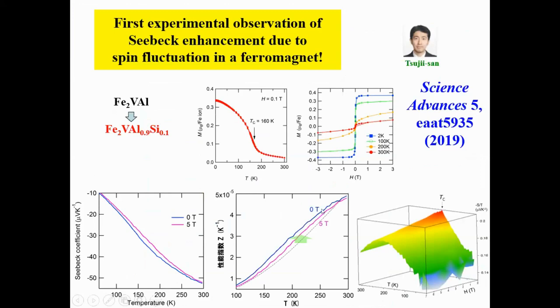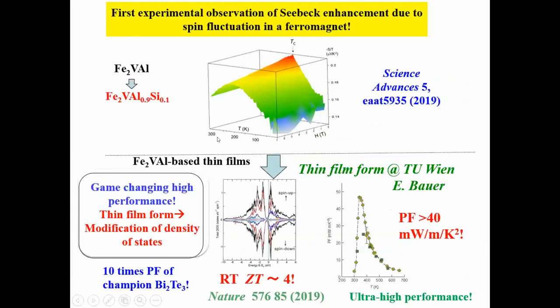And basically, this was proved by applying a magnetic field and suppressing the spin fluctuation, which shrinks the Seebeck, as shown here. And actually, this effect looks to be small here, but we only apply a small finite magnetic field, and the enhancement effect can be what we've estimated, like 50% of Seebeck enhancement by spin fluctuation, quite large.